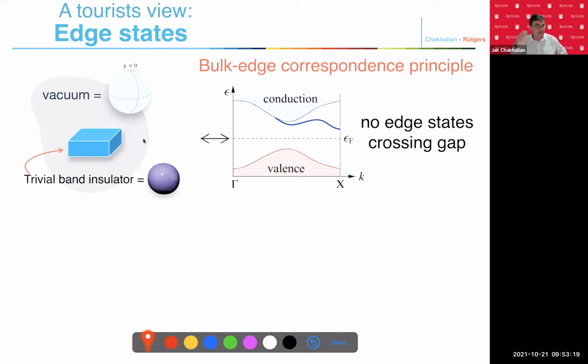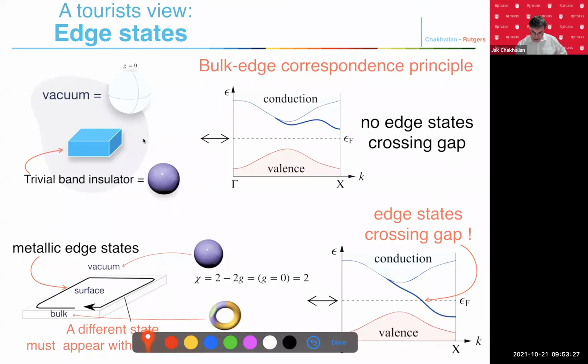And that's what we've been doing for the last 70 years, studying all these kinds of insulators. But now, let's say I have some strange insulator here, which has inside a band structure where the electrons move in momentum space which is equivalent to a torus. But the vacuum is still a sphere. And here's the interesting thing. You cannot go from a torus to a sphere without punching a hole. So punching the hole means that I need to move from genus equal to 1 to genus equal to 0. In other words, vacuum is this, the bulk is that. Then on the surface, I have to cross from genus equal to 1 to genus equal to 0.